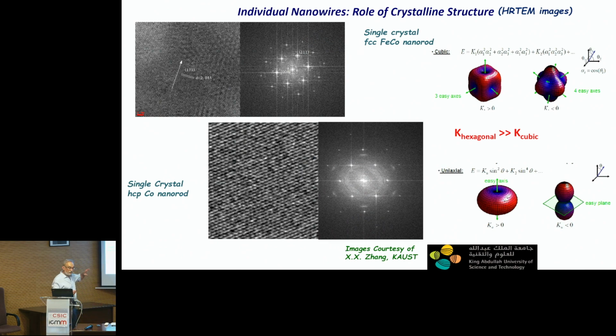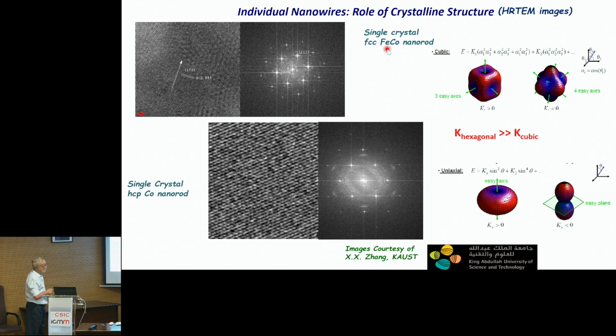You remember after this alumina membrane is dissolved. In this case, which is very different compared to the amorphous microwires, the crystalline structure is very important, because it can compete with the shape anisotropy. In fact, most of the nanowires we have fabricated have either cubic anisotropy, for example, those nanowires rich in iron or nickel, or a hexagonal crystalline anisotropy, like pure cobalt or cobalt-rich nanowires. I would like to emphasize that the hexagonal crystalline constant is much larger than the cubic. So the cubic anisotropy is overcome by the shape anisotropy. But the hexagonal anisotropy and the shape anisotropy many times have to be balanced because they are of the same order of magnitude.